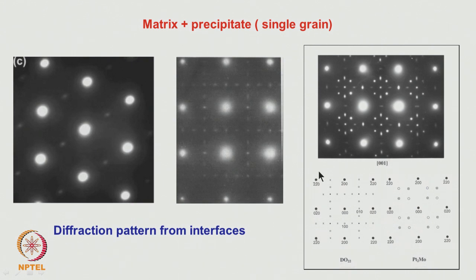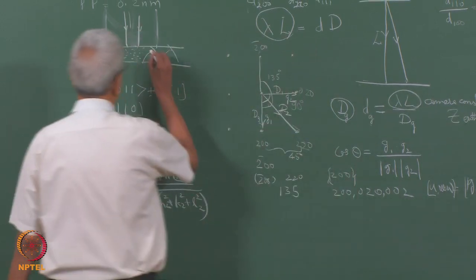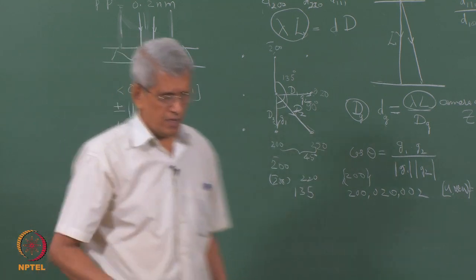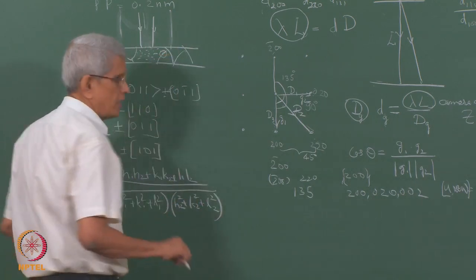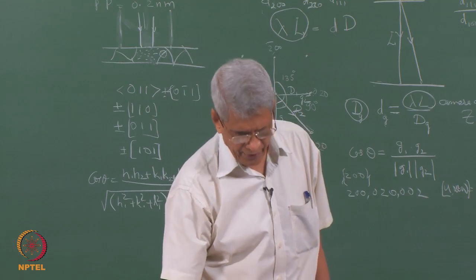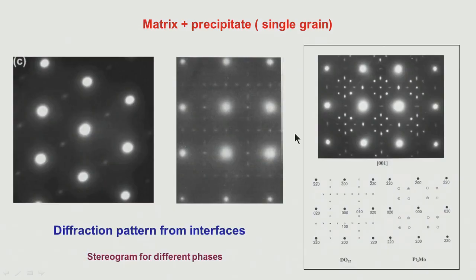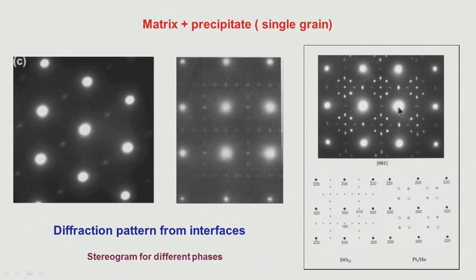This analysis is from a single grain where we have considered the matrix plus precipitate. If we want to find the orientation relationship between a grain and a neighbouring grain, or identify the interface plane, or characterize how grain boundaries look — whether low-angle or high-angle — we need to get diffraction patterns from both regions, either together or separately, and then analyse them to get information about the interface. Some of these superlattice reflections correspond to ordered phases that are non-cubic.